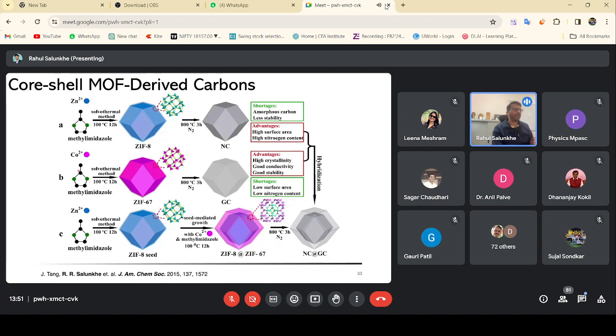On the other hand, we have another carbon, that is cobalt ion based carbon with 2-methylimidazole. It is called ZIF-67 carbon. ZIF-67 derived carbon has the advantages of high crystallinity because of the cobalt, a good graphitic degree, good conductivity, and good stability. But it has the disadvantages of low surface area and low nitrogen content.